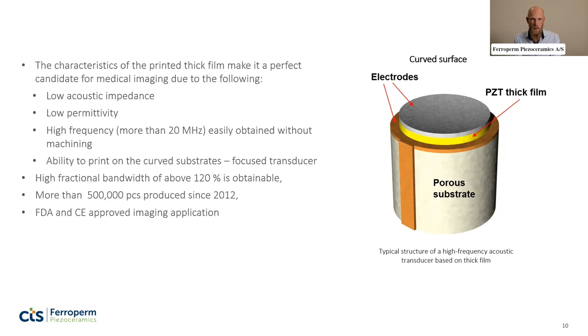So you can imagine a curved thick film with a certain thickness, and then by exciting the thickness mode of that thick film, we're able to emit an ultrasound pulse at a very high frequency corresponding to that thickness. So that's how we get up to the tens of megahertz range. And the properties of the thick film and the substrate are such that you get a very wide bandwidth transducer. You get a very damped pulse at very high frequency, which is really good for imaging.